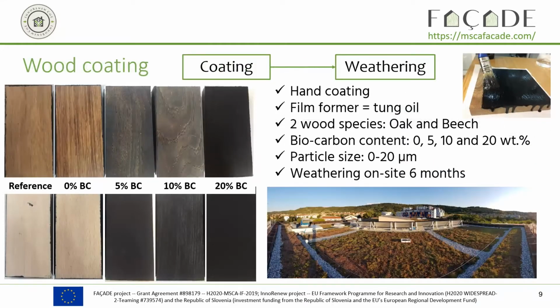Knowing this, we decided to coat the different wood substrates. So we used hand coating. We used tung oil as a film former. Tung oil is a natural oil, a vegetable oil. And we used 2 different wood species. We used oak and beech. And we took, of course, the smallest particle size. And we used different biocarbon contents ranging from 0, which means tung oil alone without biocarbon, to 20% biocarbon. So you can see on the left the different samples.